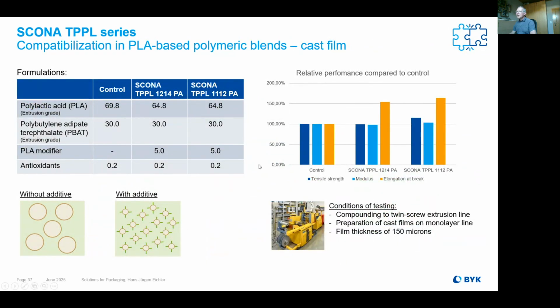And that's what you see here on the figures. We did a mixture with a PLA and PBAT with nearly 70 and 30. We did some antioxidants, and we placed in here the PLA modifier. The 1214 is a GMA material, and the 1112 is an MSA grafted material. And you see here the improvements in case of elongation at break with same values, I should say, for the tensile strength. So this gives you also an indication that these products helps to bring a better compatibilization between the polymeric blends.